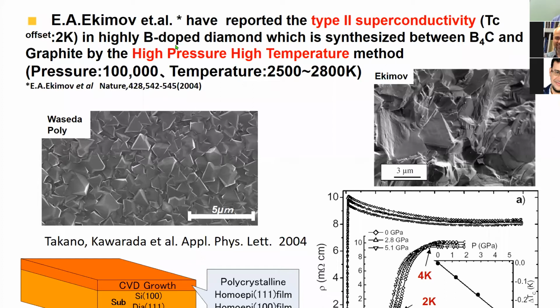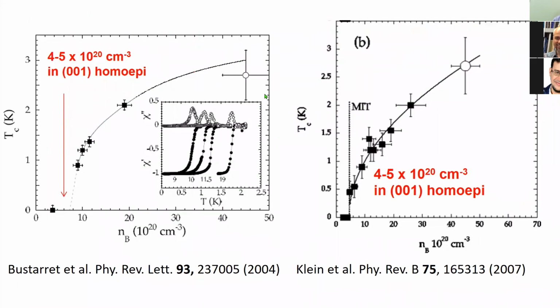The CVD method is very efficient for introducing boron inside diamond. At the same time, the French group did nice work showing the critical concentration, meaning how much density of boron is needed before superconductivity starts. This is about 5 times 10 to the 20th. Both cases show a metal-insulator transition takes place here, and the superconductor transition corresponds to the same point.